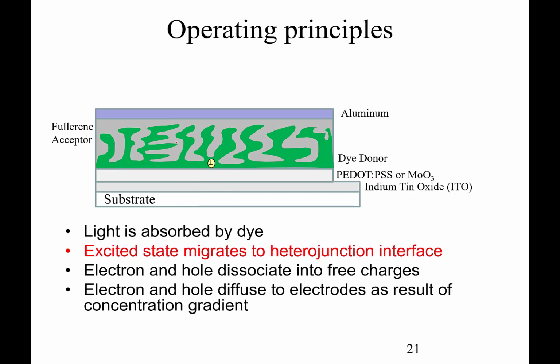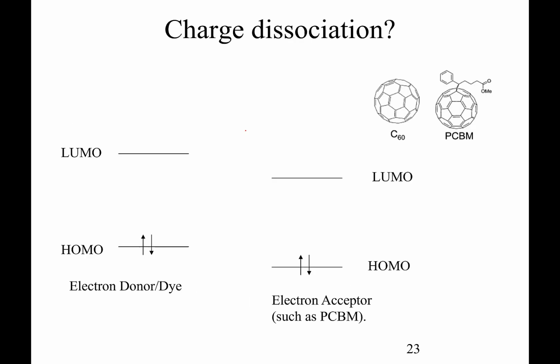Let's have a look at what happens when light is absorbed. We create this exciton. An exciton is a neutral excited state, and that exciton can migrate to a heterojunction interface. An interface, in fact, between these two materials. That's the red line in here. So that excited state must migrate to an interface. Why is that so important? The magic happens at that interface, and it turns out that at that point the electron and hole that are combined together in the exciton actually now dissociate into free charges, and that's important for generating electricity.